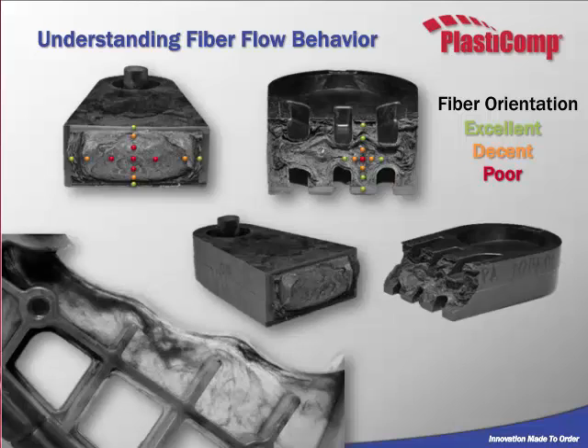On the image right next to that, we added ribbing, which we didn't really add ribbing, we kind of cored out the part, but it looks like ribs. This helps your fiber orientation drastically. You can see there are a lot more green dots, meaning excellent fiber orientation in those locations. Each rib is over 200 thousandths thick, and you're still getting that fiber orientation. Towards the center, you see a smaller localized area of poor fiber orientation. Because you're getting more fiber orientation in this part, it was able to take 200 pounds more strength than the part on the left.